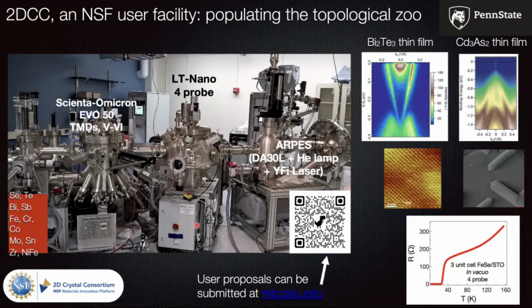This is a Scienta-Omicron, sort of a cluster tool, if you will. It's got an MBE system with all the sources that I've listed over there in red. It's got an ARPES capability with a good resolution. We've also got a helium lamp excitation, but also an yttrium fiber laser for doing additional photon energies at low energy. And then we have an LT Nano for doing 4-probe measurements. It was supposed to be also an STM. It is an STM, but it's a pretty lousy STM, honestly. I'm hopeful Omicron is not on the call, but it works beautifully as a 4-probe in situ measurement tool.